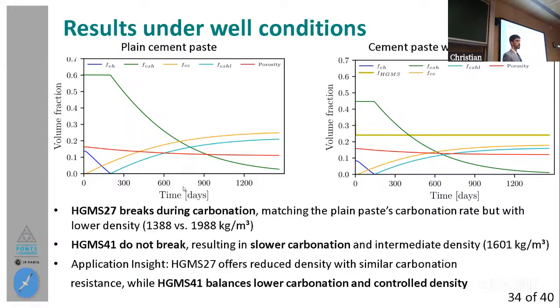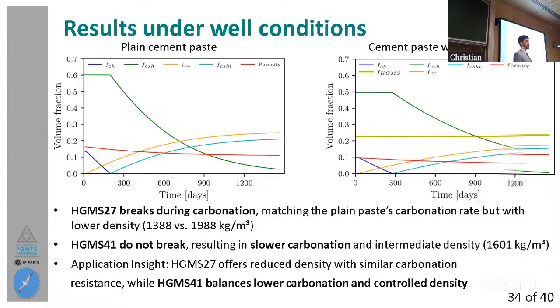If we now take a look at the results with the cement paste with HGMS41, we will see that we are not able to break the spheres at all. Then we have a decreased porosity, which decreases the diffusivity of CO2 in the cement matrix. And with these conditions, we see that the carbonation occurs slower than in the plain cement paste, with a cement paste with hollow glass microspheres, which make the cement slurry and the initial part lighter,